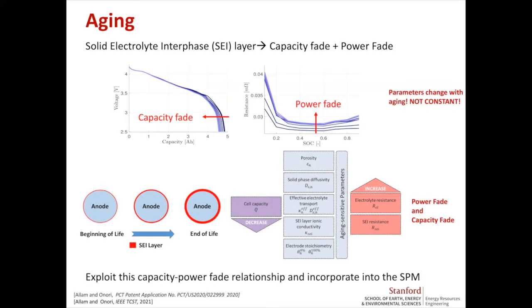We're dealing with a fresh cell in this case, and what the community agrees on is that the solid electrolyte interface is the main aging mechanism that happens at the anode, at the negative electrode, as the battery is being used in whatever application. Now, this growth in the solid electrolyte interface layer is observed through capacity fade and power fade. What that means is that in our model, the parameters will change with age and won't be constant, so they need to be updated. And as this SEI layer grows, you will see a decrease in cell capacity.